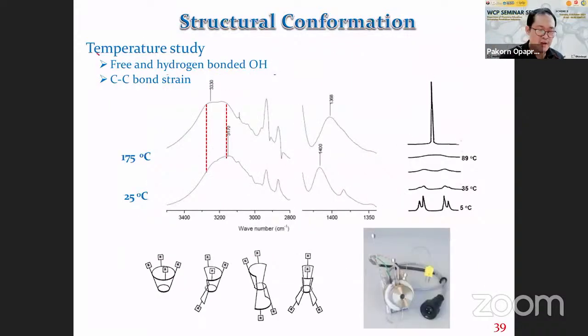We can also study hydrogen bonding as a function of temperature by using an accessory that we call heating cell. We can put sample in here. We can control the temperature from room temperature until 200 or 300 degrees Celsius and measure the spectrum as a function of time. And we can see the nature of hydrogen bonding. And from this result, we can tell what type of structural information we have in the sample as a function of temperature.